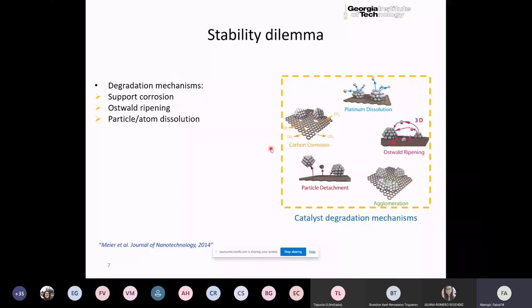The way to achieve this is to obviously break the particles down into as small a size as possible. So that's where a lot of work has gone into trying to design stable catalyst particles that are as small as possible. Now, what also happens is that when you make them very small, then they're in a metastable state. For example, if you have a nanometer sized or 2 nanometer sized particle, as you have the reaction happen over and over again, what you're going to incentivize is for those particles to migrate, or atoms from those particles to migrate and start to grow one of the particles at the cost of others. In other words, you can have an effect called ripening right here.